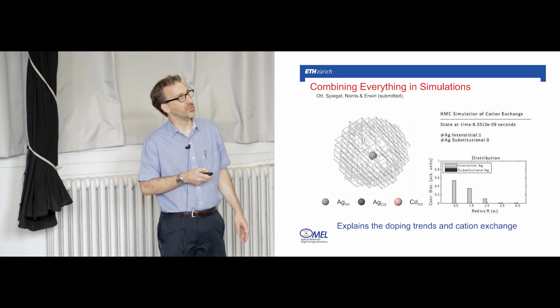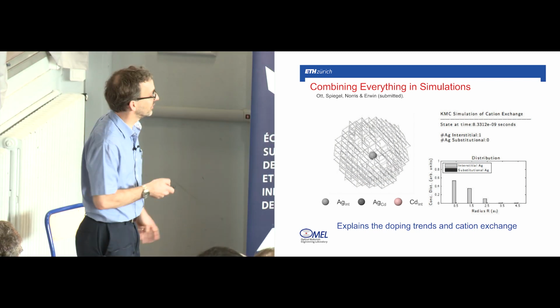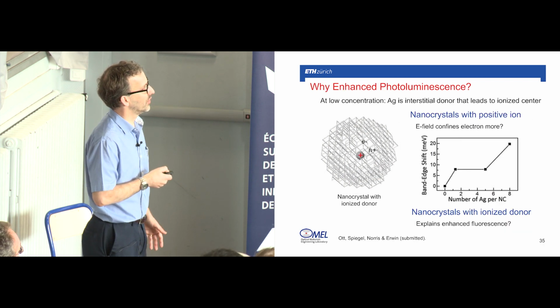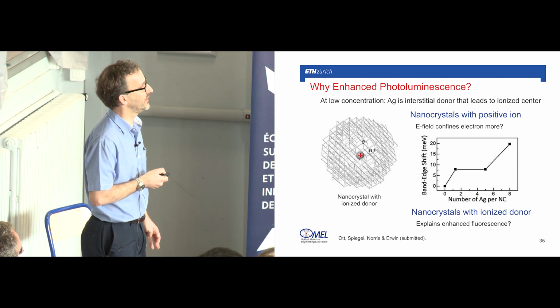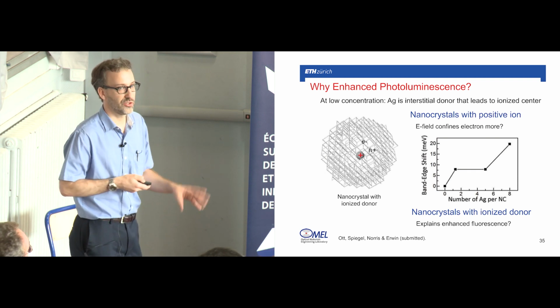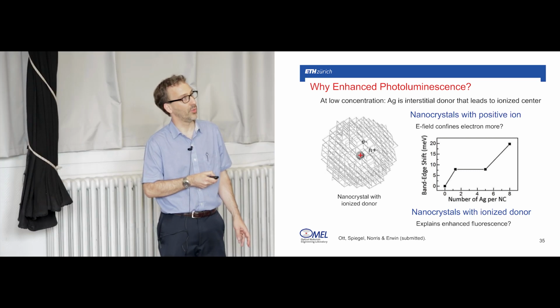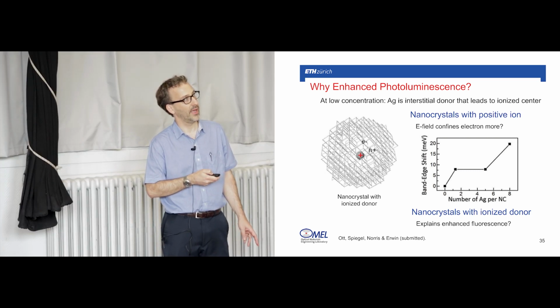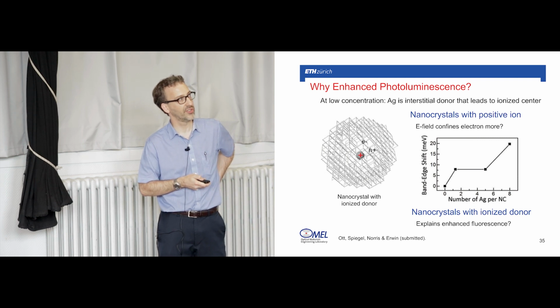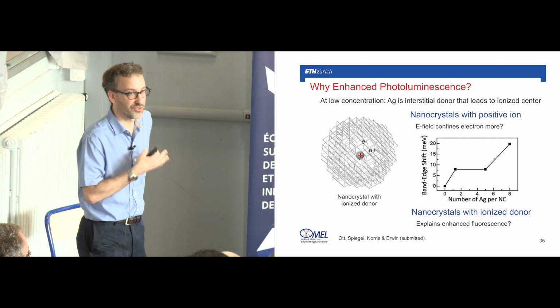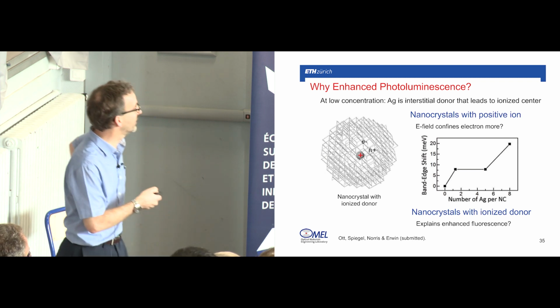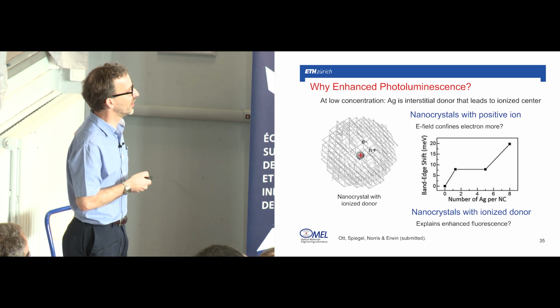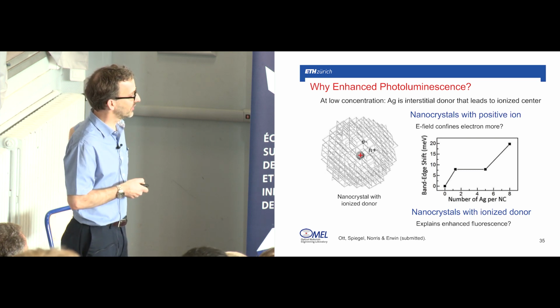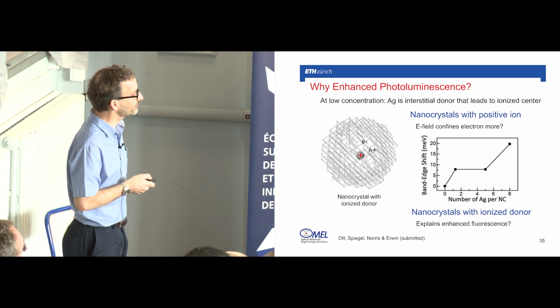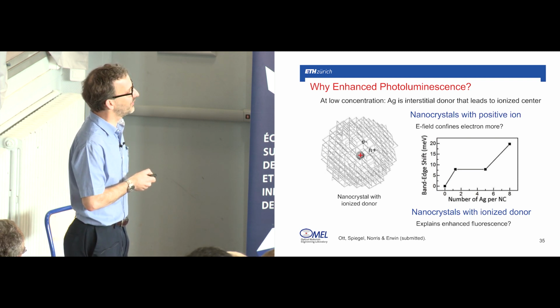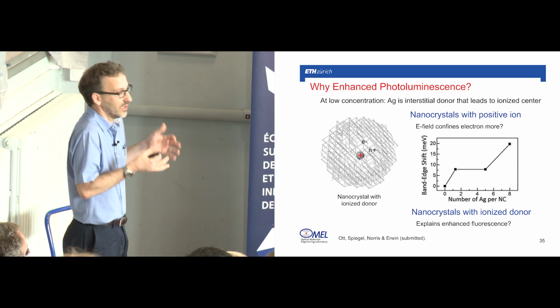Okay, the last thing I want to mention is why the enhanced photoluminescence. At low concentration, so 1 or 2, the model and all the data suggest that silver is an interstitial donor that leads to an ionized impurity. So we have something like this, and it ionizes, so we now have this positively charged interstitial. The model is suggesting that for some reason, and we have ideas about how this works but we're not ready to talk about it yet, this positive charge makes another electron-hole pair recombine more often.